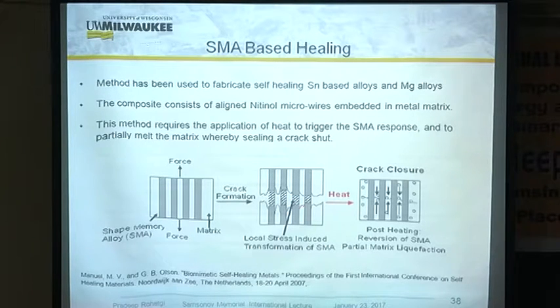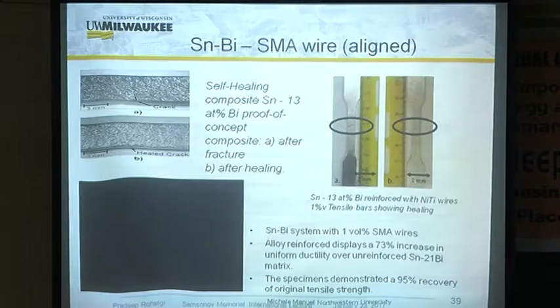Now when you supply heat to this cracked material, the shape memory alloy remembers its shorter shape, it shrinks. It shrinks and now it brings the two broken parts together, and if there is enough heat, they re-weld. So this is the route for shape memory alloy reinforced metal composite to become self-healing. And here, this is not my work, from Northwestern. You see this crack here? It has gone away. If you can see this crack here, it has gone away.